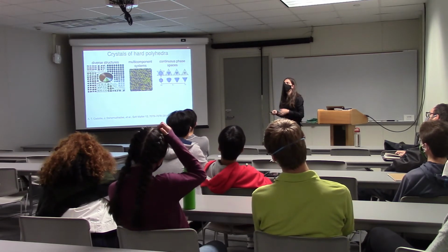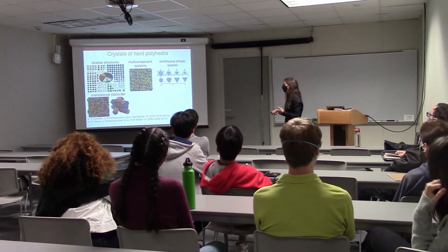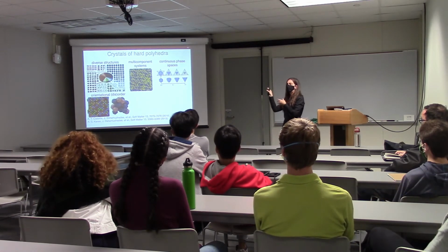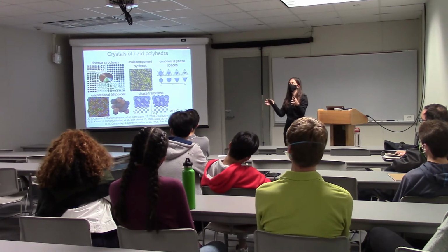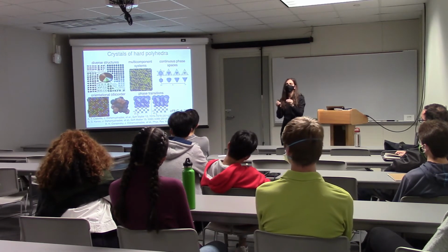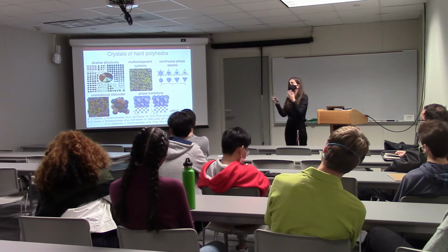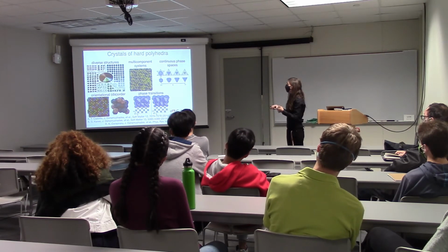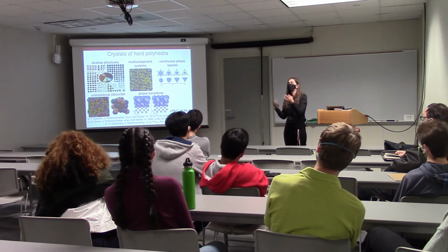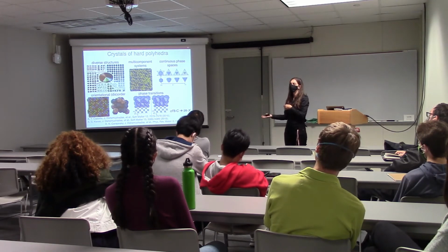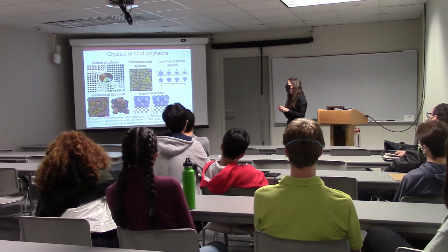You can start doing things like shaving off vertices and set up a continuous phase space, similar to, for example, changing position in an atomic system. You can see orientational disorder. You might have seen that I alluded to that in the plastic crystals. And we also see phase transitions, phase transformations. If we, for example, increase the pressure on our polyhedra, or if we change the shape a little bit, if we treat it as a parameter, or if you have a particle that you can selectively have swell instead of changing shape, you can have the system undergo a phase transition. This one here is interesting because it starts with diamond, which is interesting for photonic applications because of its band gap, and then you can force a transition to a lower symmetry structure that would have a different band gap, so you would have different photonic properties. So all those things exist in hard-shaped systems without any explicit interactions at all.